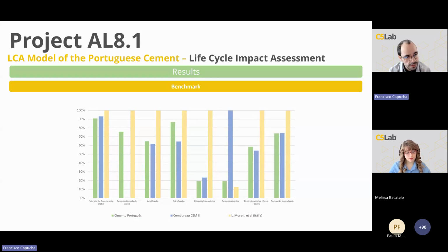In parallel, we also conducted a benchmark against some of its peers, concluding that the Portuguese average cement is equivalent to a European average CEM II cement. This is noteworthy because the Portuguese average cement includes the production of cements with high clinker content, such as CEM I, whereas CEM II is a blend with a lower clinker content. So we are equivalent to that.